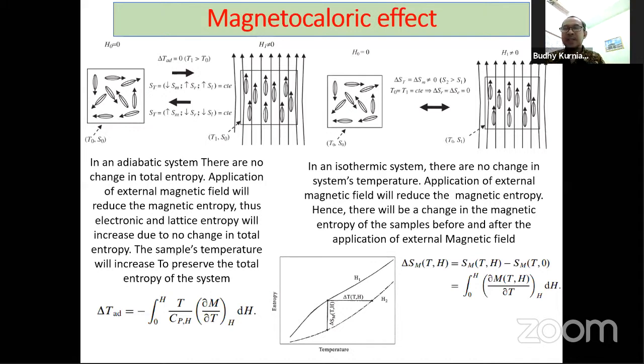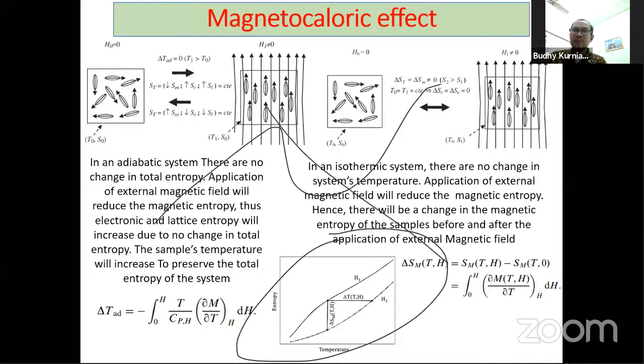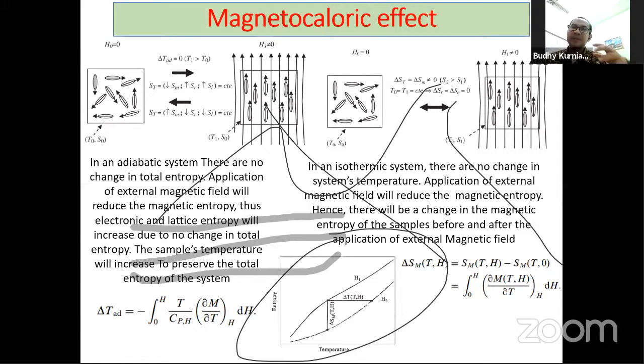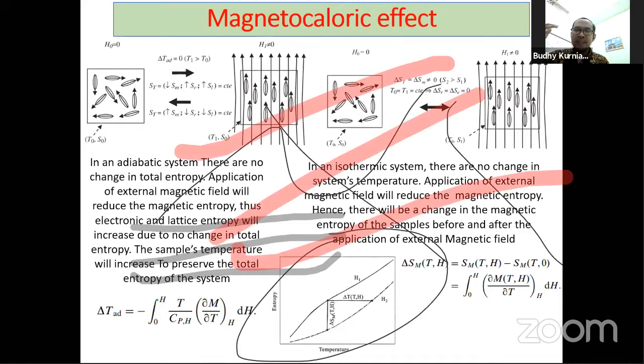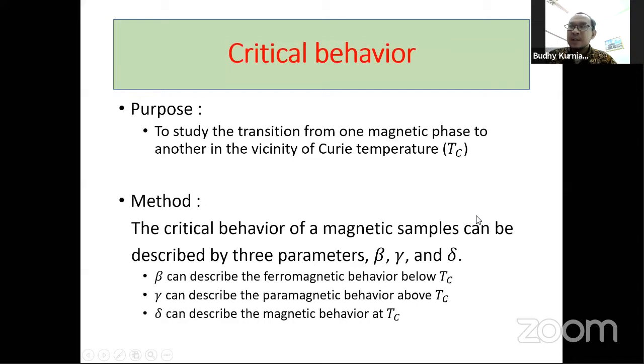measure the MH curve, the magnetization process. We measure the magnetization process from 0 up to about 7 Tesla, and we measure at several temperatures. And what kind of temperature here? The temperature here is about the critical behavior that I mentioned previously. Yeah, below TC, at TC, and above TC. That is our measurement system. Next, please.